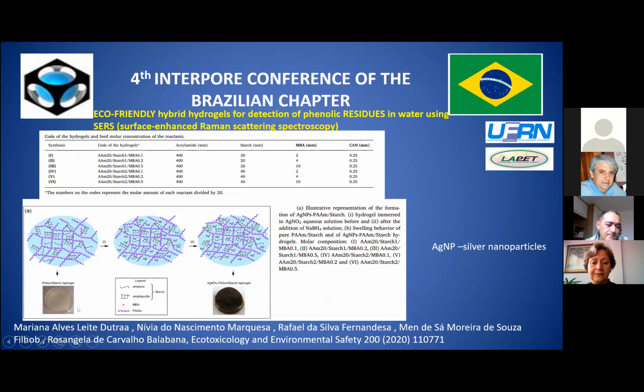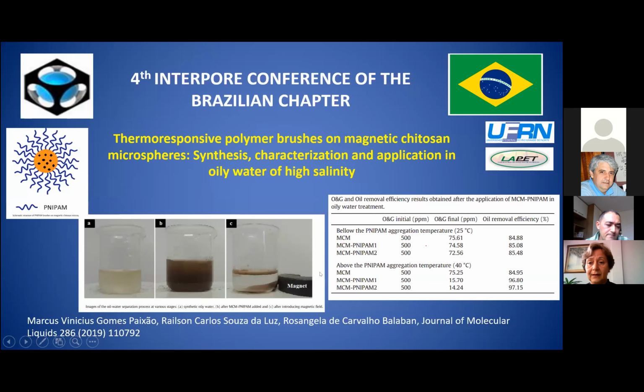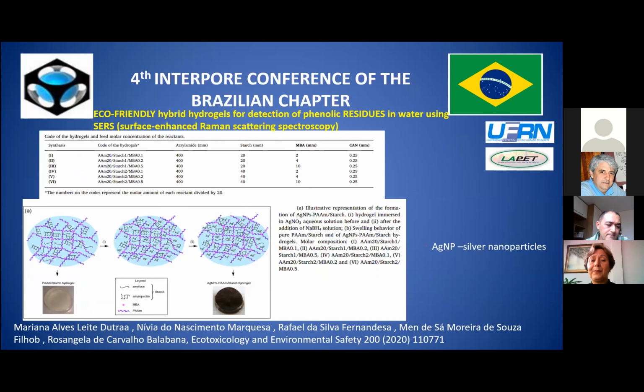In the table, we can see that a very high oil removal efficiency was obtained using this system. In another work, we prepared eco-friendly hybrid hydrogels made of polyacrylamide and starch. So you prepare different hydrogels with different concentrations of cross-linker, and we obtained very clear hydrogels.